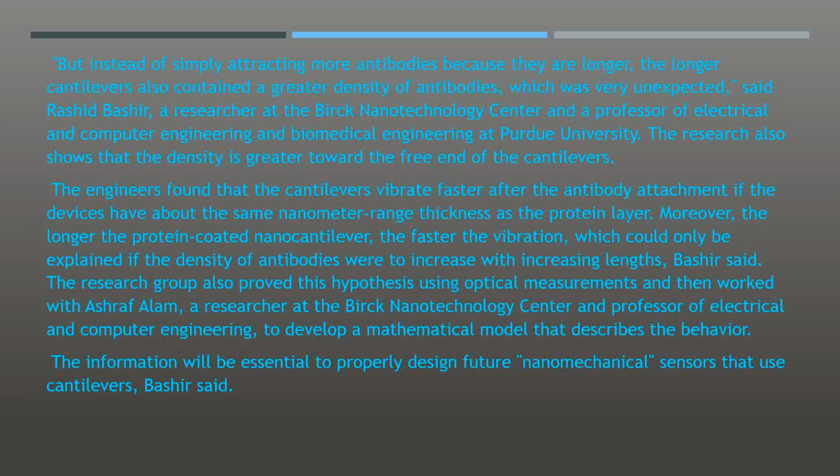But instead of simply attracting more antibodies because they are longer, the longer cantilevers also contained a greater density of antibodies, which was very unexpected, said Rashid Bashir, a researcher at the Birck Nanotechnology Center and a professor of electrical and computer engineering and biomedical engineering at Purdue. The research also shows that the density is greater toward the free end of the cantilevers.